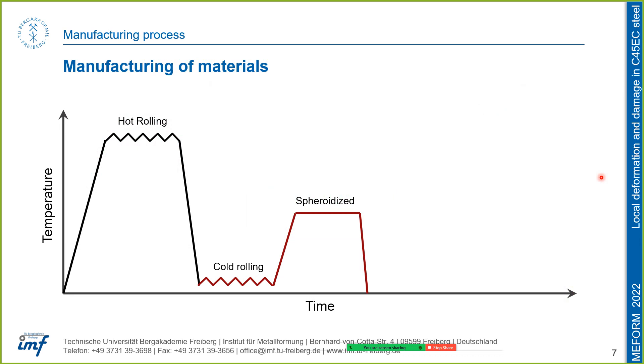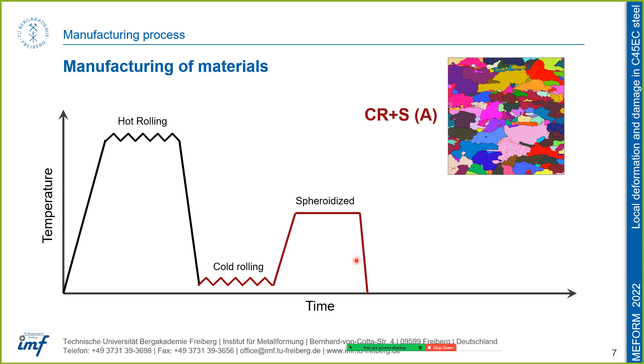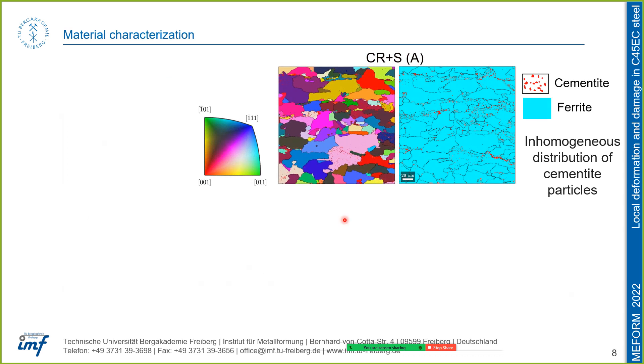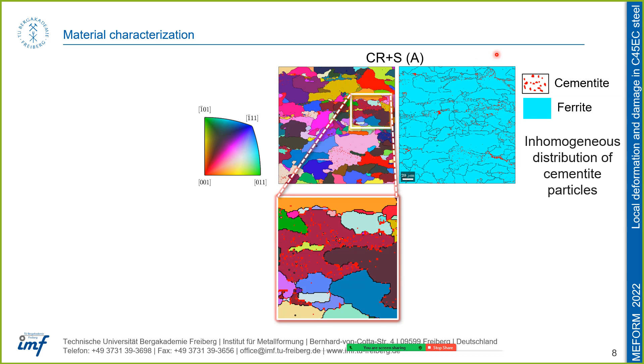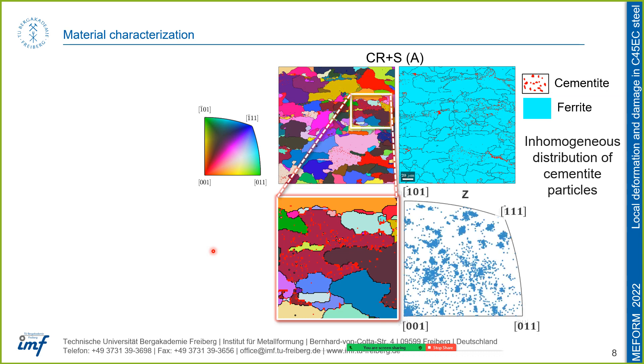For the manufacturing of material A, after hot rolling, if we do cold rolling and then spheroidization, we get a certain microstructure that is slightly aligned in the rolling direction. We see that the cementite particles are formed as bands on the grain boundaries and are not homogeneously distributed within the ferrite matrix. In this magnified picture, we can see some very small ferrite grains as well as some very large ferrite grains — there is heterogeneity in the grain size distribution.